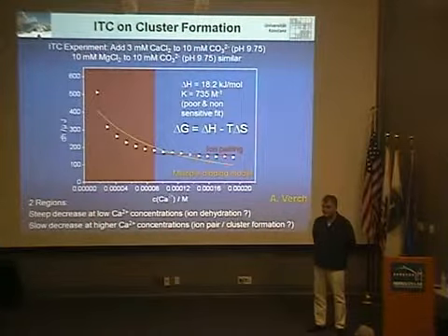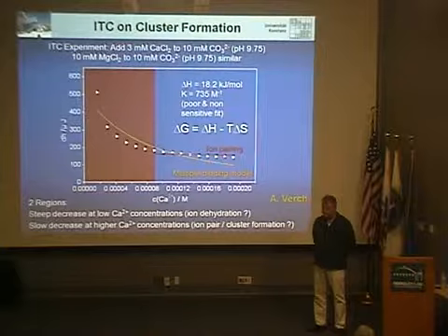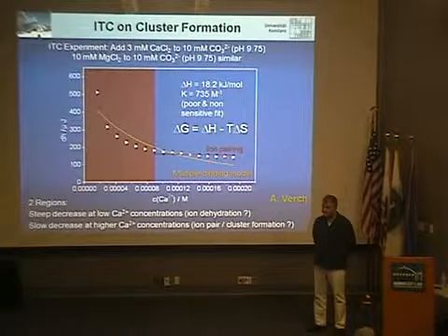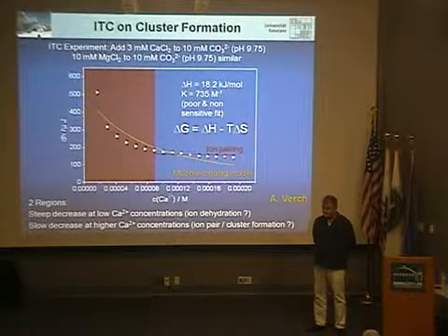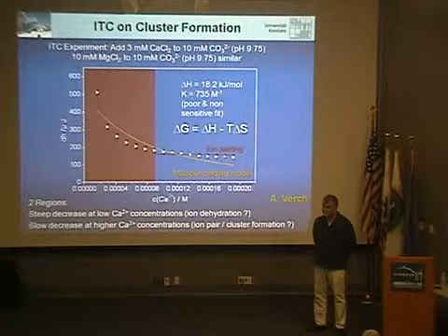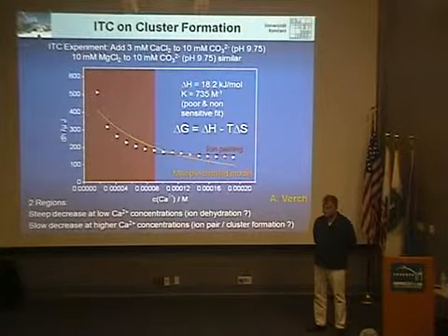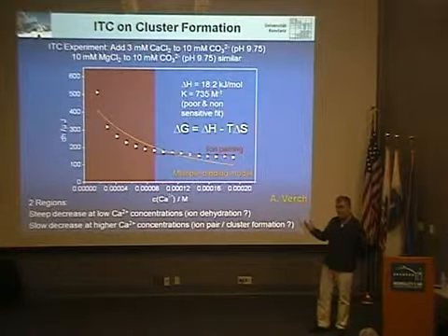Yeah. We found that magnesium caused these kind of delays of incubation time. So I would be really interested in your work if there's a correlation between presence of magnesium or anything. I'd be interested in anything that causes these delays before the titration curve starts to rise. That may tell that there's a delay in getting one ion out of being associated either with water or with the polymer additive. You definitely detect them quantitatively.